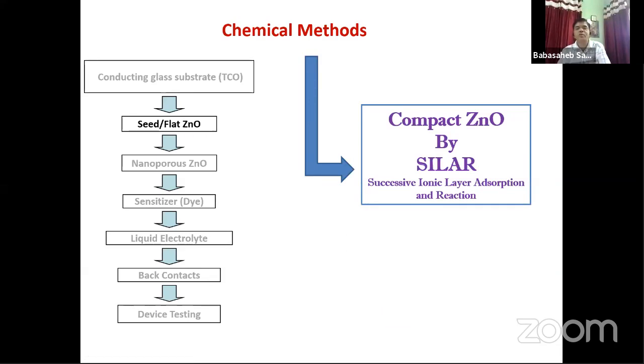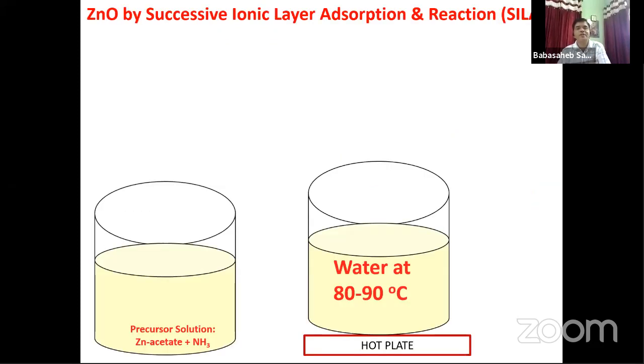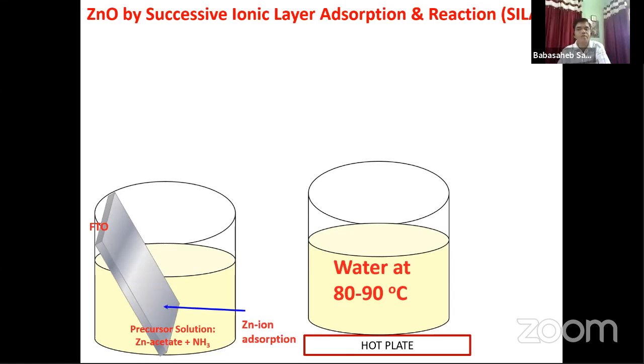First I wish to demonstrate how we have used this SILAR method. As it is based on separately placed cationic and anionic precursor solutions, you dip the substrate into the separately placed cationic and anionic precursors. We have taken an FTO coated glass substrate and dipped it inside the zinc acetate solution, which is complexed with ammonia. Then there is an adsorption of the zinc ion on the substrate surface.